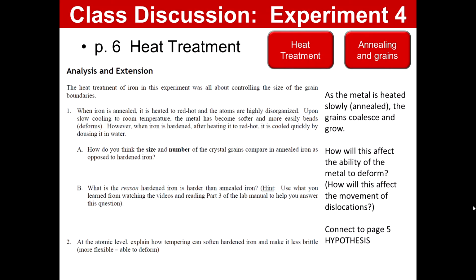So to finish this up, we are looking at the analysis and extension on the lab report, and so hopefully that previous video that you just watched from Steve Mould will give you some indication of what's going on, as well as the little bits of reading in the previous part of the lab where we talked about the heat treatment. I just want to leave you with a final visualization of what happens when you anneal something. So annealing was the first thing that we did, heating it up in a very slow manner and just letting it cool down gradually. Or when you did the tempering part where it was very, very hard, annealing is the slow gradual heating of the material to change the grain size.